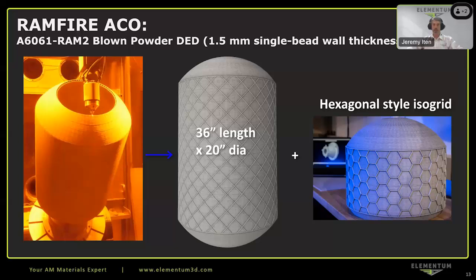In the center, you can see a diamond type isogrid around the outside of that part. Again, to give the scale, it's about 36 inches in length, so it is quite sizable. It's bigger than you'd be able to print in a typical laser powder bed fusion type bed system. But with the robot DED assembly, you can get very large, 20-inch diameter. And then on the right, that part there is shorter in height, but the same diameter, and you can see that's a hexagonal type grid structure.